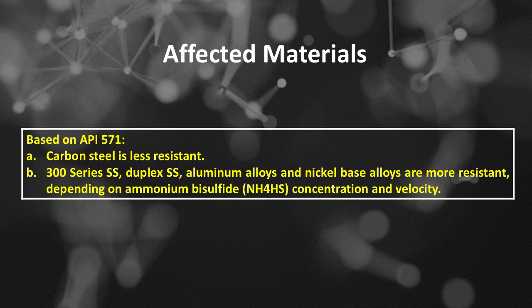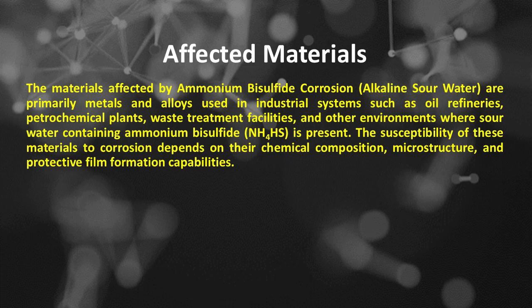Ammonium bisulfide corrosion or alkaline sour water affected materials, based on API 571: A, carbon steel is less resistant; B, 300 series SS, duplex SS, aluminum alloys and nickel base alloys are more resistant, depending on ammonium bisulfide, NH4HS, concentration and velocity. The materials affected are primarily metals and alloys used in industrial systems such as oil refineries, petrochemical plants, waste treatment facilities, and other environments where sour water containing ammonium bisulfide or NH4HS is present. The susceptibility of these materials to corrosion depends on their chemical composition, microstructure, and protective film formation capabilities.